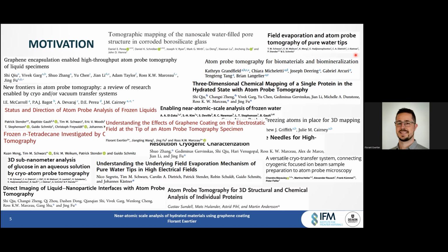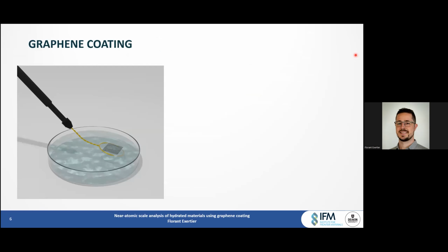So let's move on to graphene coating that I mentioned before. In this study, it was used to improve the conductivity of a non-conducting sample. I will explain a little bit about this later, but here's a brief overview of how it works. I purchased the graphene as chemically vapor deposited on copper foil. So the copper needs to be removed using chemical etching. And at the end, we obtain a graphene foil that's floating at the surface of water in a Petri dish, like this.